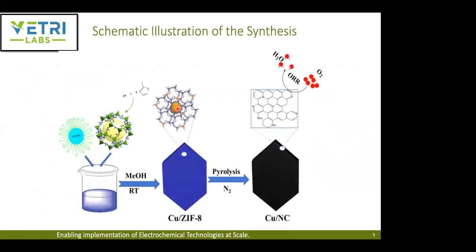This is to give an overview of the schematic illustration of their synthesis. They mix copper nanoparticles and the ZIF-8 formed from the zinc 2+ and the linker, and they sonicate it, and then stir it for about 1 hour in a methanol mixture at room temperature, and they form this copper ZIF-8. Then to form the Cu/NC, the copper ZIF-8 needs to be pyrolyzed, and they do this in a nitrogen atmosphere to form copper-doped nitrogen-doped carbon.